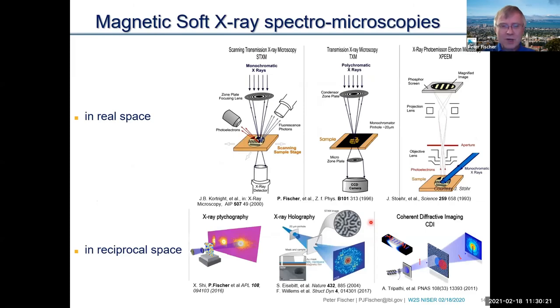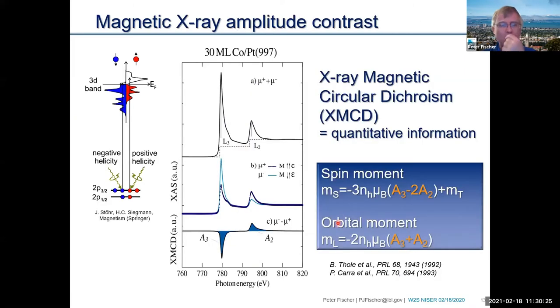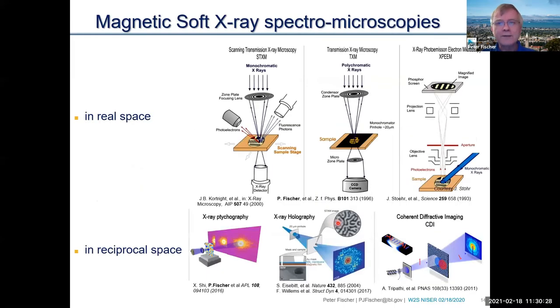Okay, now this contrast that I just described can also be used for imaging. And a whole zoo of techniques has been developed that use this XMCD and XMLD contrast for imaging the spin texture with spatial resolution, because as I mentioned two slides earlier, the length scale of these X-rays is in the nanometer regime. That means the spatial resolution that ultimately can be achieved with X-ray microscopies is in the nanometer regime. And that's of course the length scale of interest for magnetic imaging.